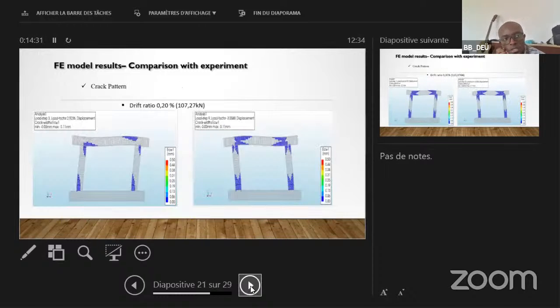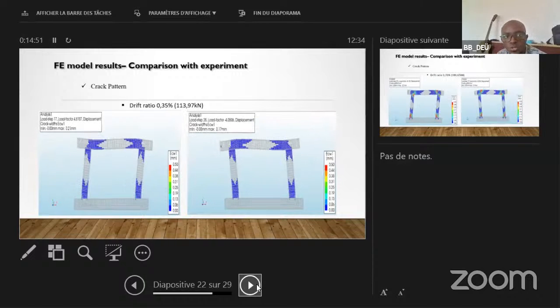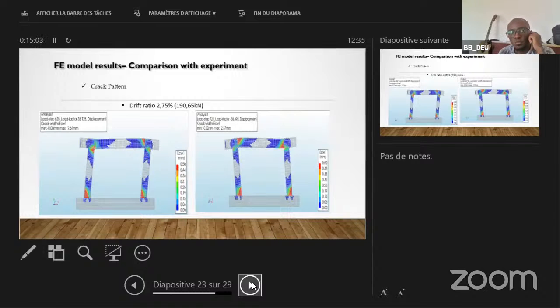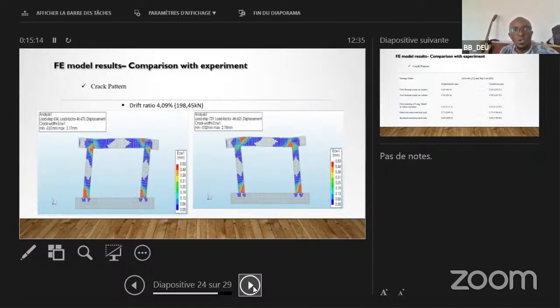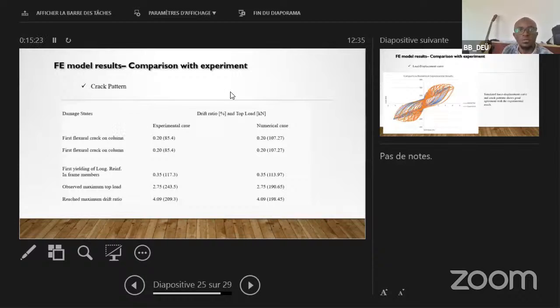And talking about the crack pattern, we get, at a drift ratio of 0.20%, 107.27 kilonewton. And at a drift ratio of 0.35, we get 113.97 kilonewton. At the drift ratio of 2.75, we get 190.65 kilonewton. And the last one, we get 198.45 kilonewton. So we can compare here the table at the drift of 0.